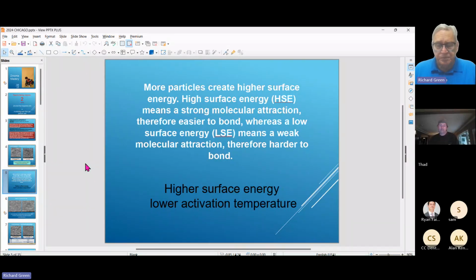Now, when we're talking about sintering, we pre-sinter everything. All of our discs, when you get them, we've already sintered up to about 1,000 degrees centigrade. And so nothing happens much below 1,000 degrees centigrade during the sintering process. That becomes kind of the activation point. When you run it up to 1,000 degrees as fast as you can, that's when the action starts. And when you have smaller particles, you have lower activation energy. You'll note that on our rapid sintering, our 1 hour sintering program, we're only sintering up to about 1375 or 1400, which is a lot lower than most people are accustomed to sintering.